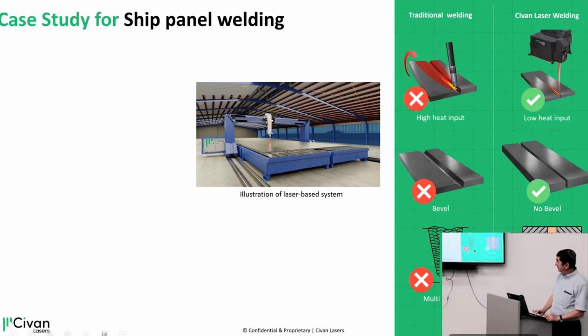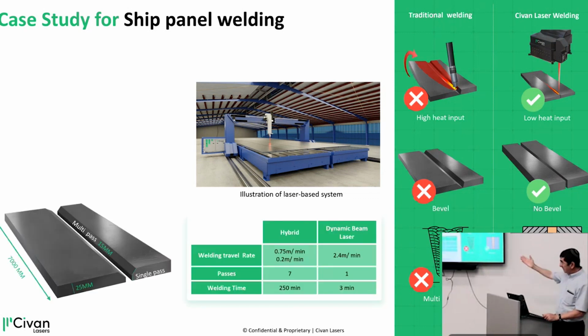And the most important disadvantage is that you have to go tens and sometimes hundreds of times with a filler wire. In order to avoid a huge heat affected zone, you don't weld everything at once, but every time you weld just 1 millimeter, maximum 2 millimeters at a time with a filler wire. So if you have 25 millimeters and you have the bevel, you have to go about 40 times back and forth, each time filling up with a filler wire. With a laser, you just go one time and you're done. So, for example, this is an example that we worked out with a customer who ended up buying a laser. This is a 7-meter length of a weld.